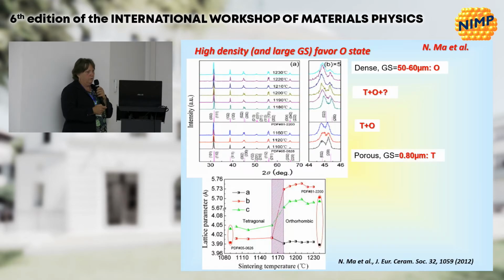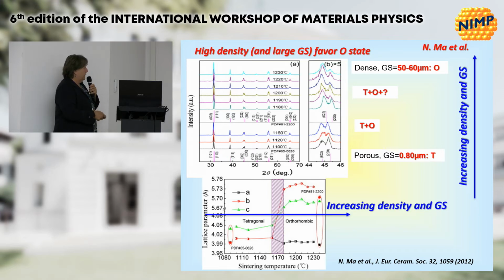Of course, the room temperature property should be affected by this phase superposition. And there is a paper from about 10 years ago in which they used similar sintering parameters to ours, and indeed they also obtained a tendency from tetragonal, which is found for small, fine grain sizes and porous samples, because here there are two parameters, porosity and grain size, determined by the method used to sinter the samples, and the tendency towards the orthorhombic state for dense materials with high grain size.